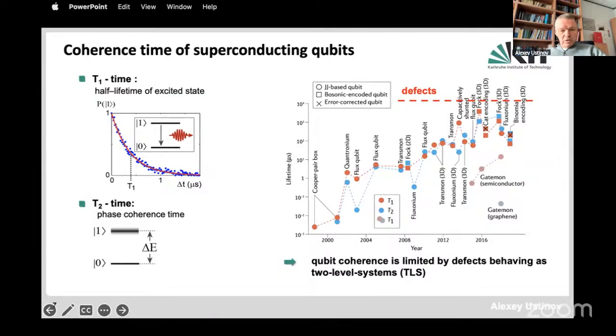In the beginning, the progress was almost exponential over the first 15 years, but then the progress was very strongly slowed down. And currently, the coherence times of the superconducting devices are in the range of, let's say, a fraction of millisecond or a millisecond. So the primary source of these limitations of the coherence times has been identified over those years, and this source are microscopic defects which occur in the material of superconducting electrodes of circuits. So that's basically a subject which I'm going to focus on today.